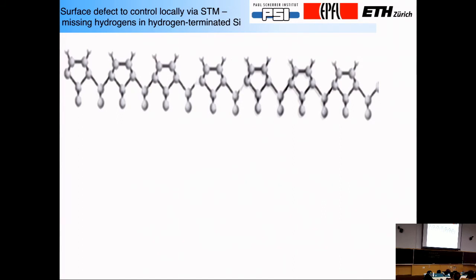You've broken inversion symmetry, and there are a lot of unhappy electrons. And these are called dangling bonds. And these dangling bonds have a great affinity to be attached to hydrogen atoms, which you might insert into your vacuum system. So typically, what you do with a silicon 100 sample is you so-called passivate the dangling bonds using hydrogen, which are these little atoms on the top of this figure.